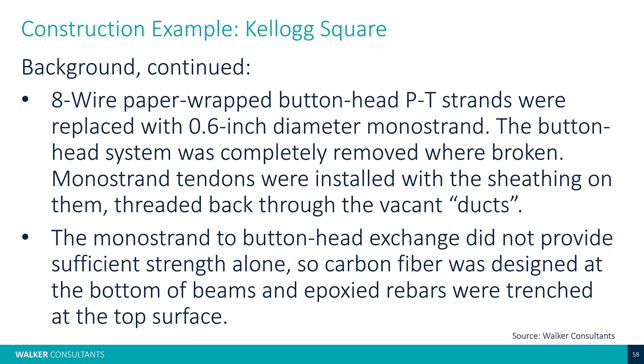So we already talked about the 8-wire paper wrap button head PT system. The repair approach that we were doing was we were actually pulling that out of the paper wrap sheathing. We're going back in, cleaning that void out, and then we're sticking in a 0.6 diameter monostrand. So this example that I have with me is a half inch, a 0.5 monostrand. So the 0.6, if you imagine, is a little bit bigger around. We were able to work with the contractor to get the sheathing and the tendon pushed back through these voids so that we can replace with a fully encapsulated system into the existing vacant ducts, if you will. So that worked out really well.